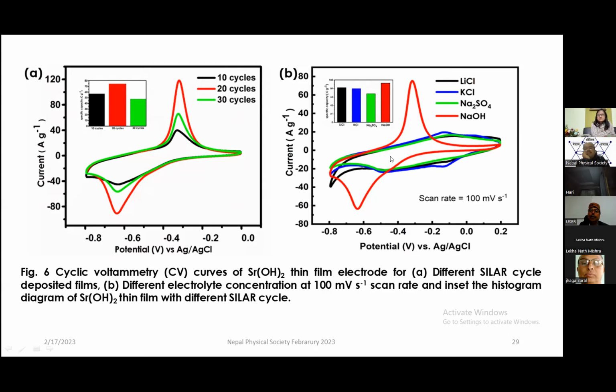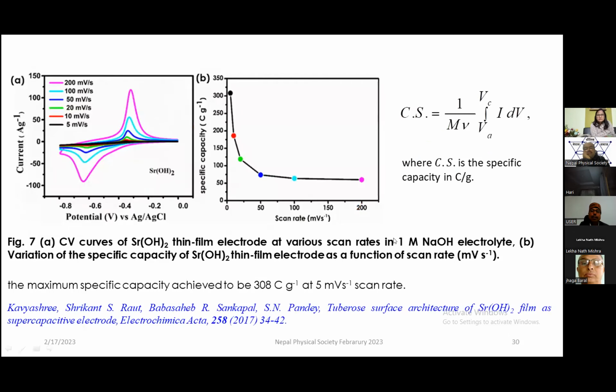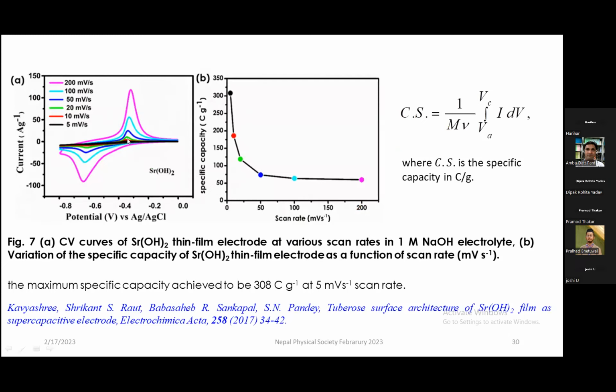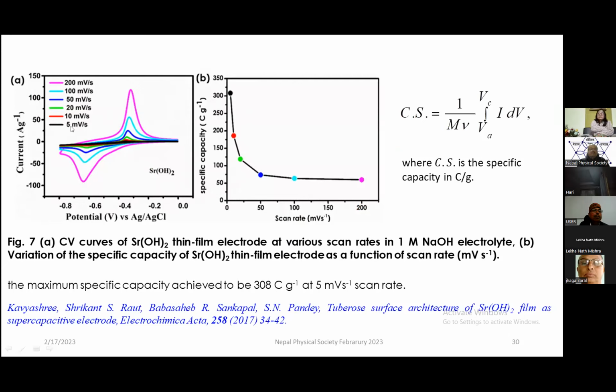A lot of research is going on to take a particular material and see in which electrolyte it gives the best result. Here we have analyzed that NaOH gives the best result. So the number of cycles is 20 and the electrolyte is NaOH. Now CV at various scan rates: we have taken 1 mole NaOH, and at various scan rates we plot the current against the potential. We get the best result at 5 millivolt per second scan rate, where we get this maximum value.